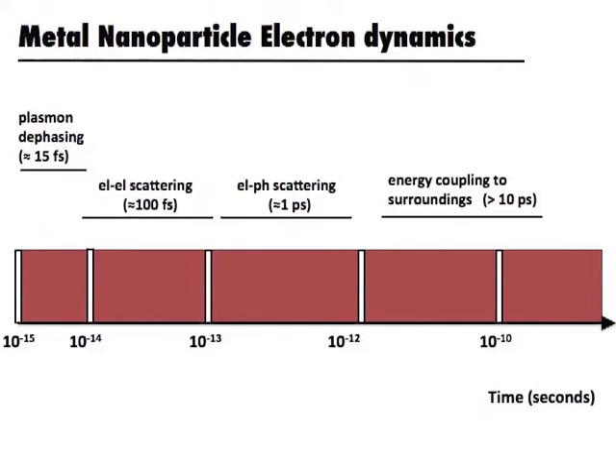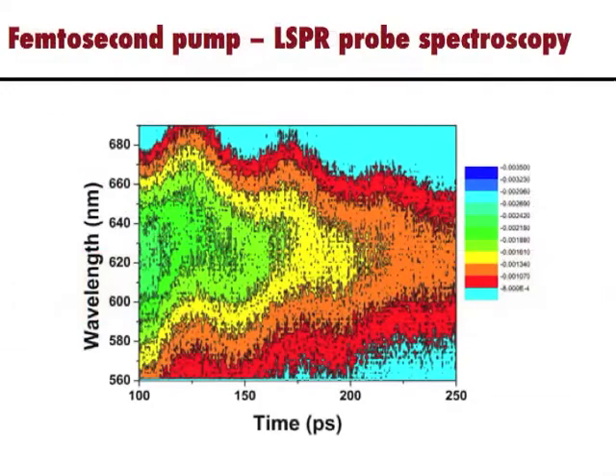Measurements of the plasmon line width with femtosecond time resolution provide a static snapshot of the interfacial properties. A typical example is given here, which shows the parameters that can be retrieved from experiment. These are the plasmon center wavelength, peak width, and signal amplitude, all measured as a function of time. In our perspective, we use these data to describe how nanoparticle morphology influences electron relaxation dynamics, and in turn the nanostructure's sensitivity to its environment.